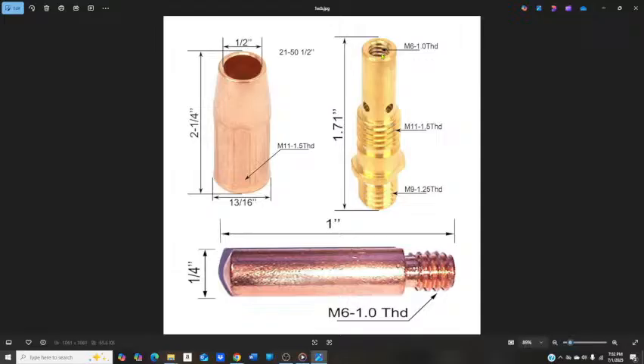So if you're replacing your liner and you buy a liner that's too long, when you hold the torch as straight as you can, you want to cut your liner so it just barely is inside here so that these threads can start. You don't want a gap between this and the liner because it's a place for the wire to get balled up. Any gaps here or at your wire feeder, you'll get a bird's nest in there, and then you have to cut it all out and pull all the wire out. You lose all that welding wire, and then you have to drive new wire through and start over again.